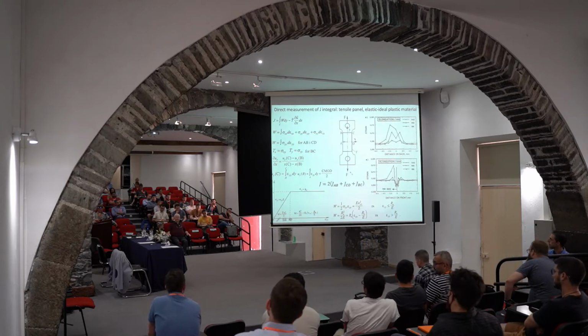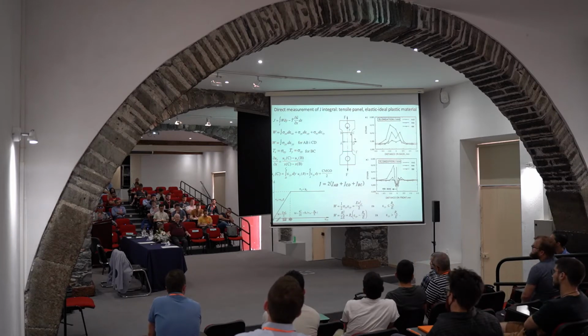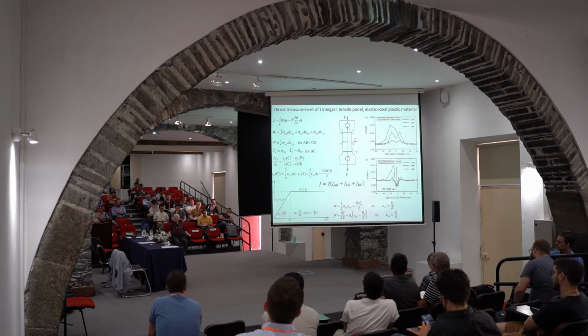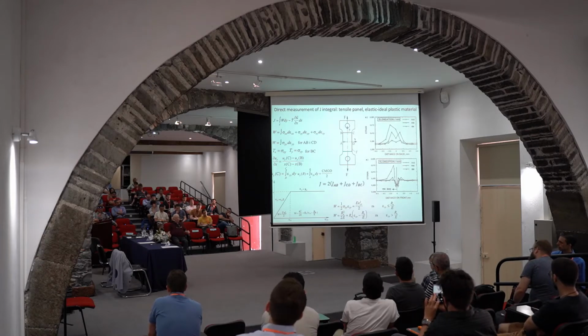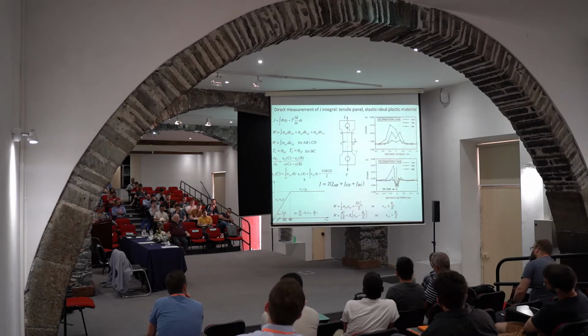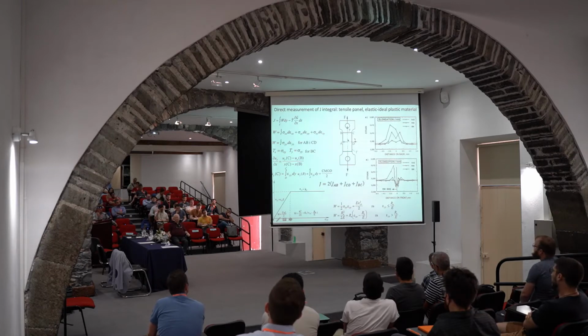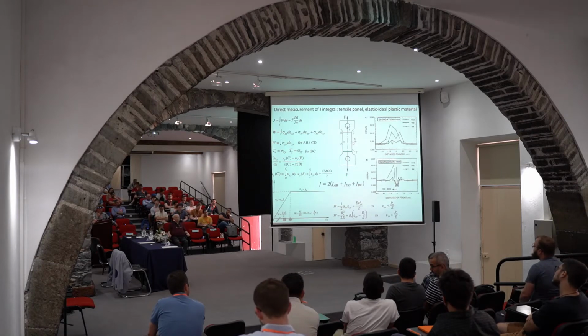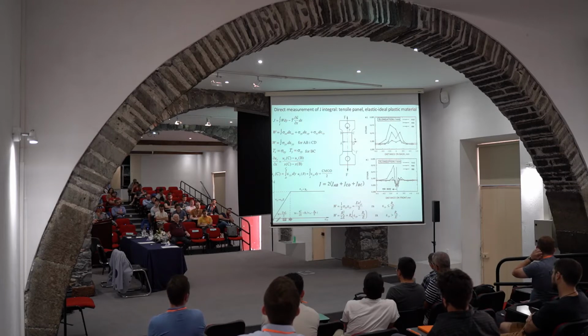Well, maybe people will go back to this excellent experimental technique, because in this case we directly measure J integral. We don't need all this stuff to prove that what we are really measuring is really a measure of J integral, as in the case of standard experimental evaluation. So what J is physically represented with here are these strains. You can see some real measurement here. This is on the back side, the uncracked side, and here there is a cracked side. So the difference between these strains is actually J integral.